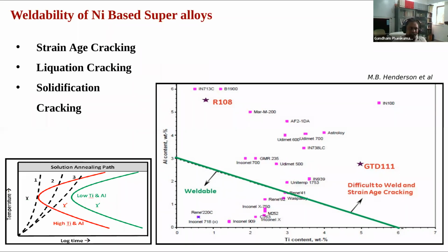But unfortunately, in the case of superalloys, nickel-based superalloys, you will have all three of them present. Okay, so if your luck is like that, then you will have all three possible cracks. And you must understand how to eliminate one after other in a very careful manner. So in a printed component, you can avoid all of them if you are very careful in the choice of processing conditions and also to minimize the homogenization treatment. Okay, so that is some direction of research these days.